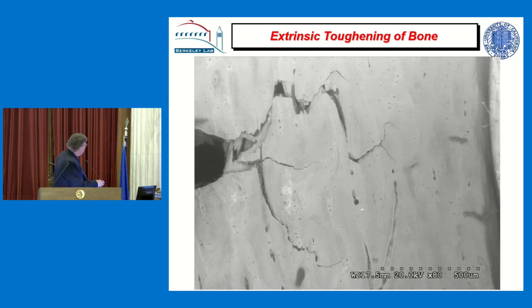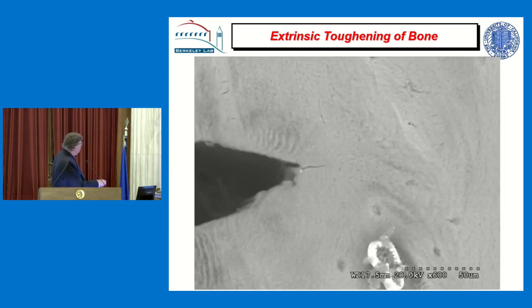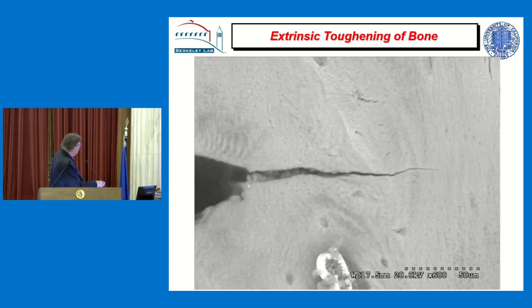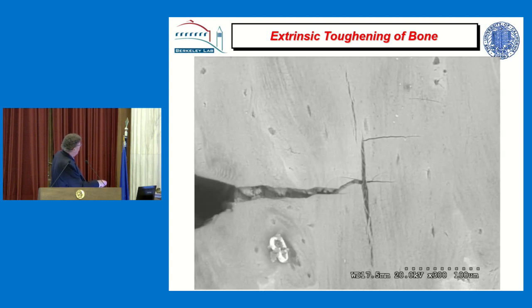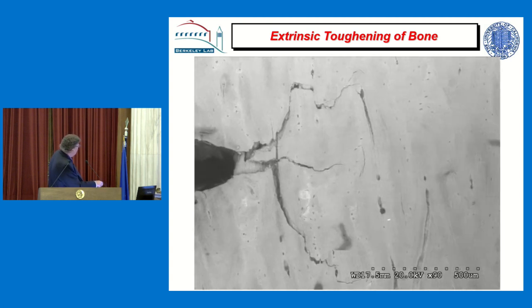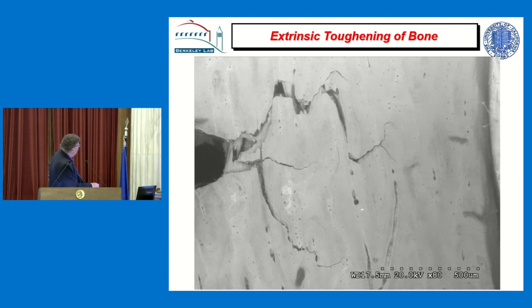A crack propagates here, and it encounters an osteon, and you can see as it encounters that osteon, it immediately deflects. You can see little bits of fibers that bridge that osteon, and the result is a complex configuration of tiny cracks, which actually are quite a resistance to fracture. So bone's a fascinating material in that regard.